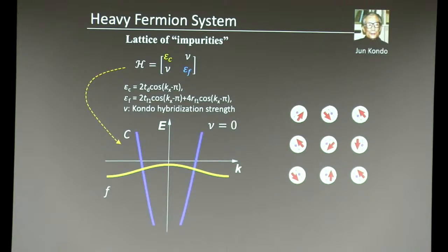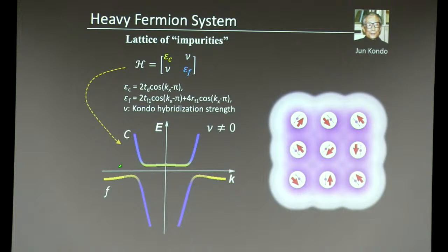As you cool down, the interaction between these localized moments and the conduction bands gets stronger and stronger, and that has two consequences. First, this F band, which can lie anywhere below the Fermi energy, gets pushed up to the Fermi energy due to the strong interactions. Second, it creates a hybridization between the F band, which is the flattish band, and your conduction electrons, and that creates a gap.